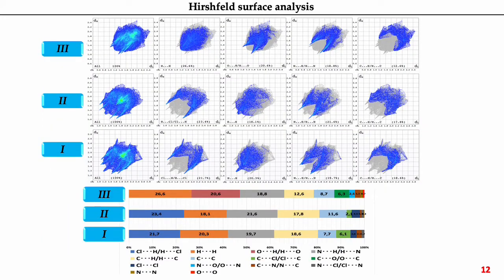The overall two-dimensional fingerprint plot indicates that the most significant contacts for compounds 1 and 2 are Cl...H, H...H, N...H, and C...H. However, in compound 3, the most significant contacts are H...H, O...H, N...H, and C...H. The difference between them is due to the presence of different substituents.